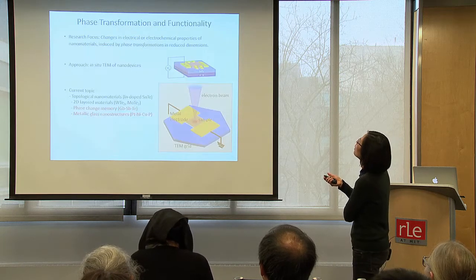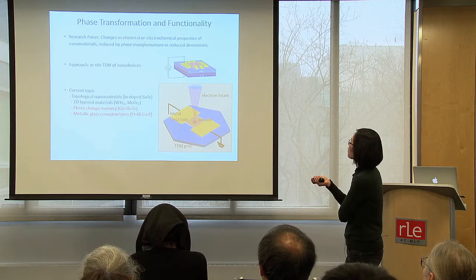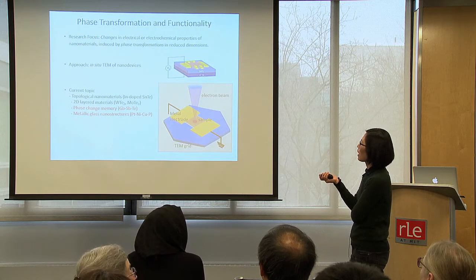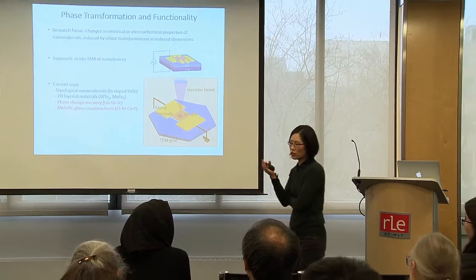I just showed you how we use the in situ heating holder. This is an in situ heating electrical holder. One use was to do a lot of just heating and then study crystallization dynamics, and the other was to actually run devices. For the electrical pulse, we are using nanosecond type pulses. And when we look at the shapes out of the oscilloscope, it's pretty good, right? There are no capacitive or inductive elements that would slow down or change the pulse shape.